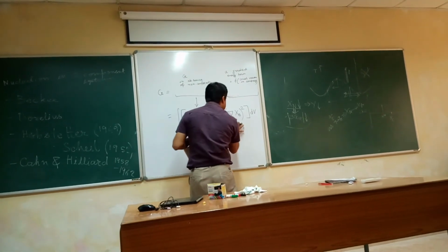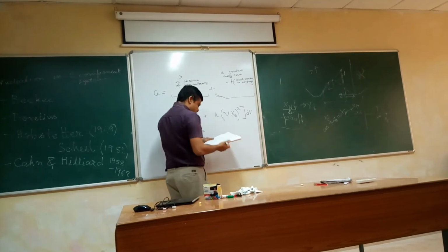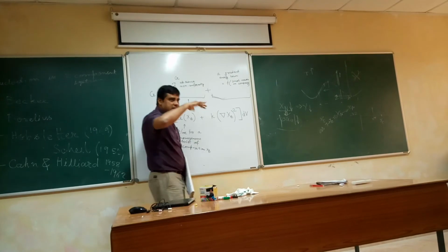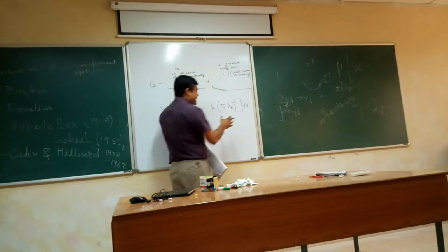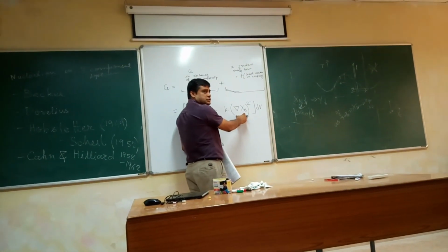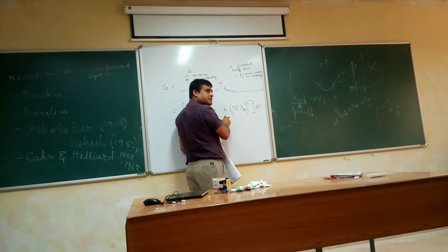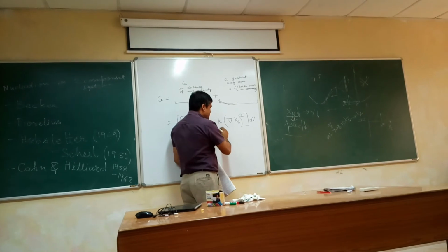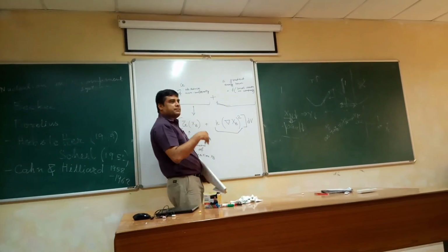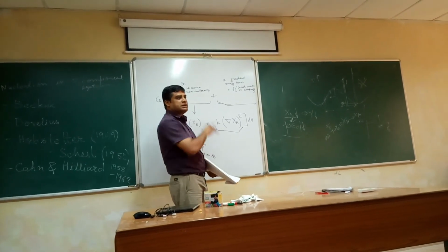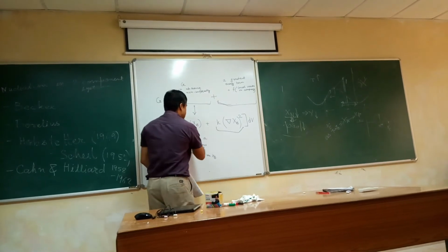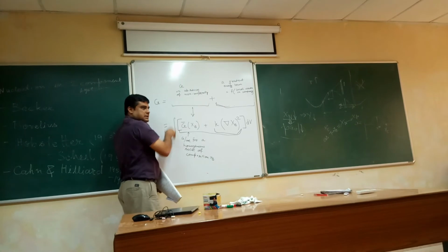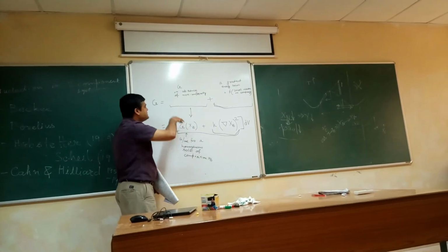And this gradient term, because of local fluctuation in composition, there is a gradient in the composition term. So square of that multiplied by some parameter which takes care of the curvature. So this gradient energy term takes care of the local fluctuation in composition. So the Gibbs free energy, and this is per unit volume multiplied by dV. So volume elements, you integrate it over the space.